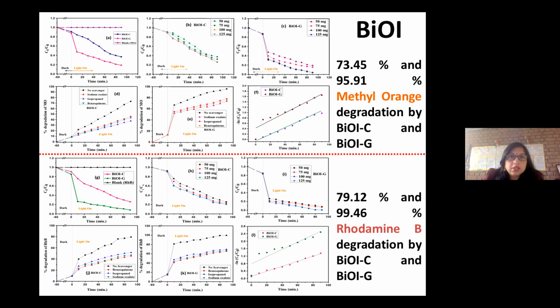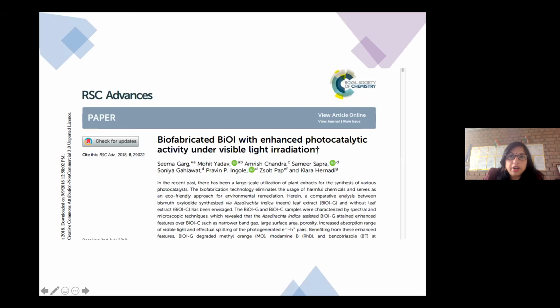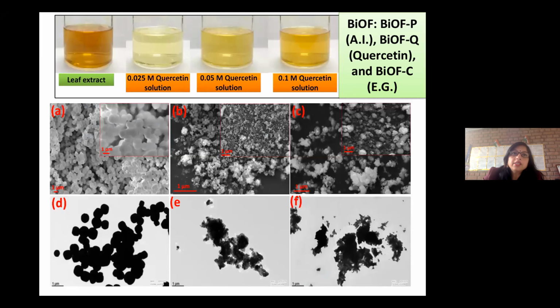The other results showed that it is giving better activity than BiOI-C. And if we compare it with the chloride and bromide, it has a higher result, higher degradation. It showed rhodamine B and methyl orange were degraded. Now, in a leaf extract, which constituent can be responsible for the process? So for the leaf extract, we used quercetin, which is available in all leaves, and different concentrations of quercetin solution were prepared. And this is the A method, where BiOF was prepared,